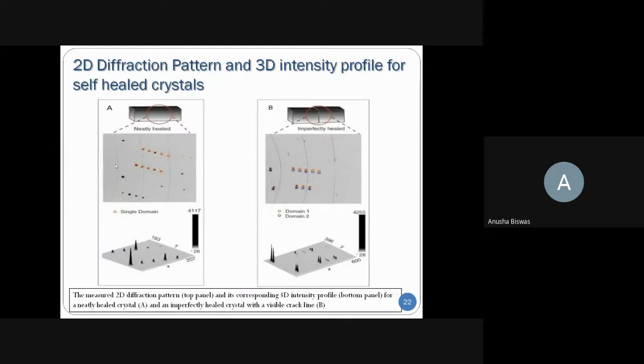Here X-ray diffraction is performed to know about the crystallographic alignment. In the case of a neatly healed crystal, only one sharp peak is found in the intensity profile. Therefore, it implies that there is only one crystallographic domain present to diffract the X-ray. But in an imperfectly healed crystal, two sharp peaks are found in the intensity profile. Therefore, there should be two crystallographic domains which are diffracting the X-ray in different ways. Therefore, the misalignment of the broken faces is confirmed again.